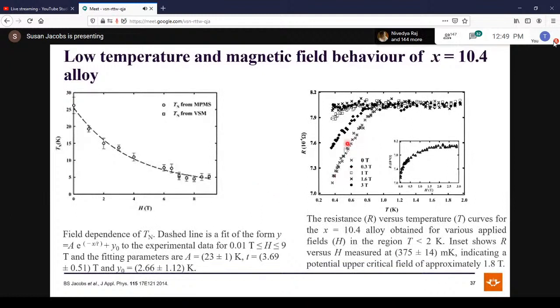But we also saw some superconducting tendencies in this alloy. So here we have the resistance as a function of temperature for the 10.4 alloy for the different fields. And the inset shows resistance as a function of field at very low temperature. So this is at 375 millikelvin. And there appears to be an upper critical field of 1.8 Tesla. So we published these results.